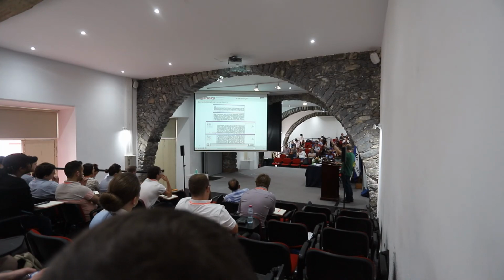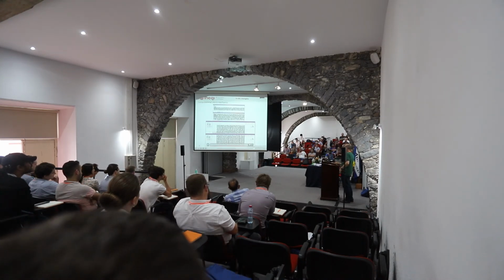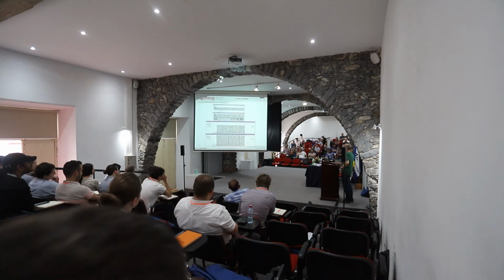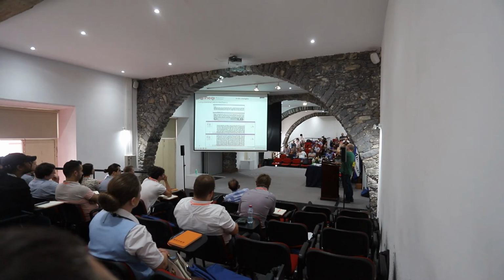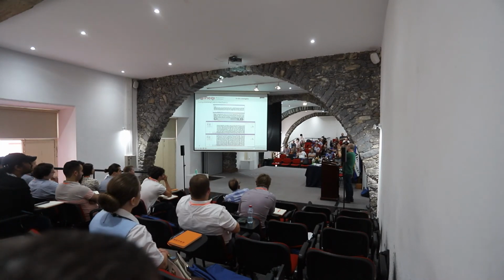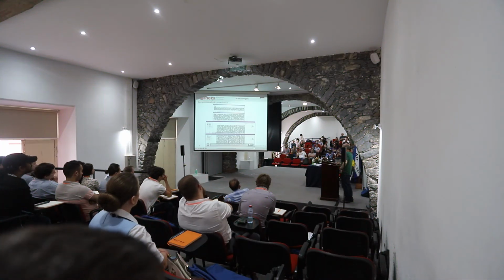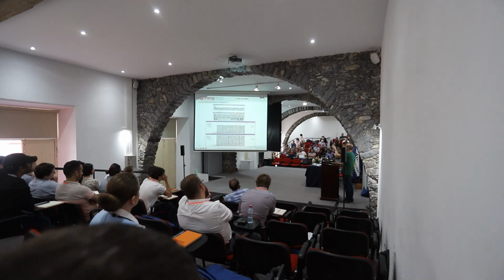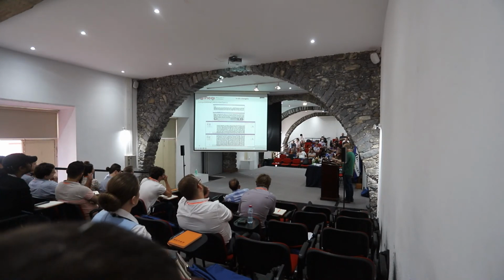Remember from Griffith's analysis that you have a relaxed stress state, right? So the probability of developing a crack there is very low. But these regions are smaller as you decrease the thickness. So here you have a higher crack density because this relaxation is not as pronounced as here. But here you just get a network of fiber matrix debonds.